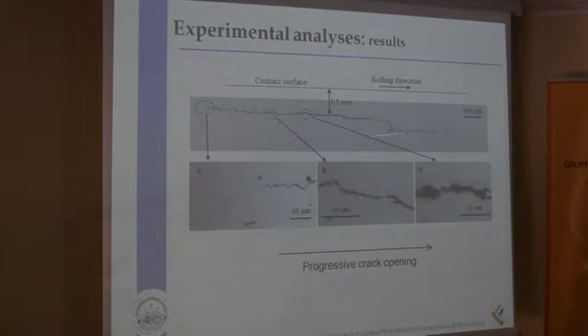It is a quite long crack, about 3 millimeters, and examining it in detail, we can note some particularities. The first one is a faceted fracture morphology, which is typical of shear propagation, especially near the crack tip. Another peculiarity is that the crack opens gradually from the tip to its central zone, and in the central zone the gap reaches a few microns.